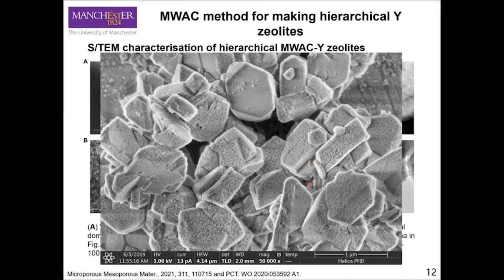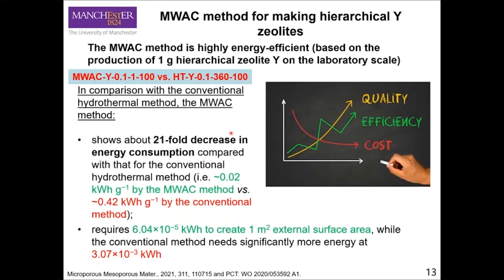Accordingly, this may seem quite childish to colleagues in industry, but because the whole development was done in my research lab, I can only do a very preliminary analysis of the economics. Based on the production of 1 gram of hierarchical zeolite Y on the laboratory scale, we see a 21-fold decrease in energy consumption for the new method we developed compared to the conventional one.